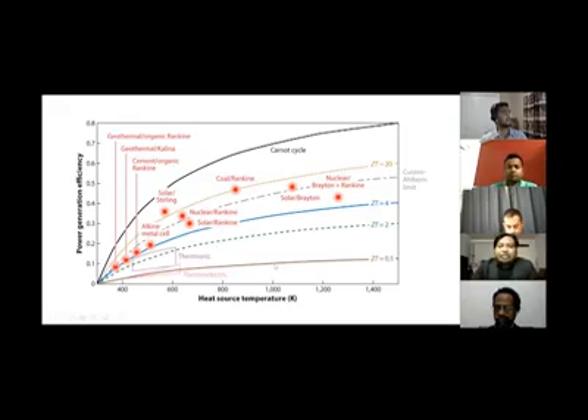So if the operating temperature of your thermoelectric material is 1000 Kelvin and the ZT value of your material is 0.5, then you can find the efficiency of your material is around 10%. So if you know the ZT of your material, from the efficiency equation you can find the efficiency of the material.